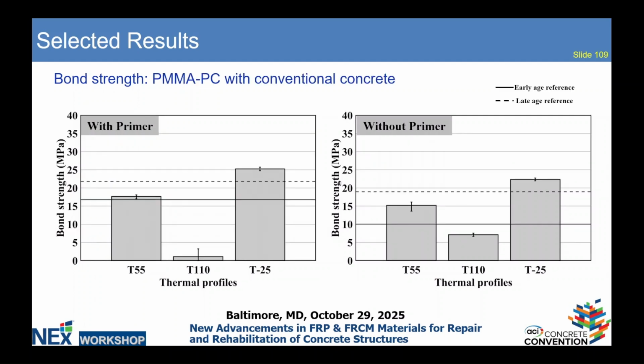Now, the interesting results come here, where this is the result of a bond test between polymer concrete and conventional concrete. The solid line and the dotted line are the benchmarks that we defined of the same set of categories, or the same test performed without the thermal samples, the baseline test. So, as you can see here, we performed the test with primer and without primer. This is the case for polymethyl methacrylate polymer concrete.